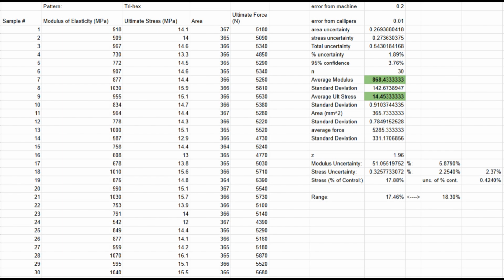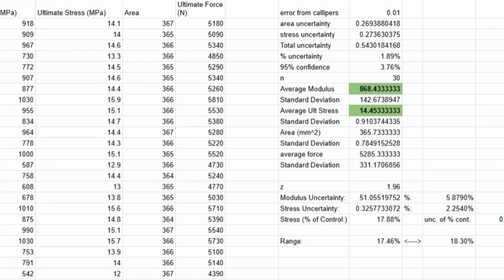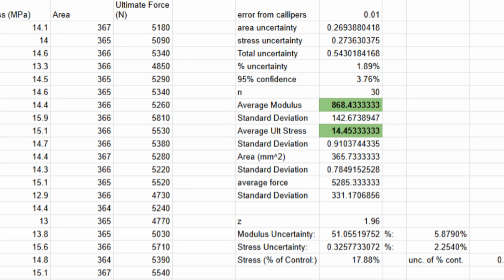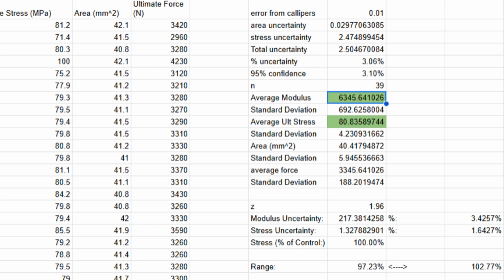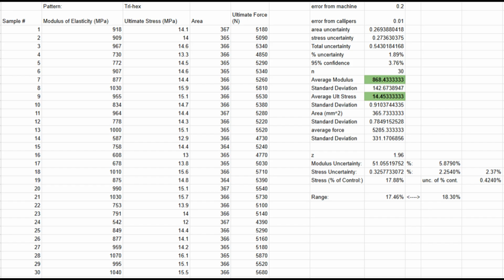Comparing our data to the requirements and constraints set by our control criteria, we found that our best result was with the trihex infill pattern, with an average ultimate stress of 14.45 megapascals and a modulus of elasticity of 868.43 megapascals, compared to the control test with 100% infill, with 80.84 megapascals for the ultimate stress and a modulus of elasticity of 6,345.64 megapascals, or roughly 18% of the ultimate stress and 14% of the modulus of elasticity, respectively.